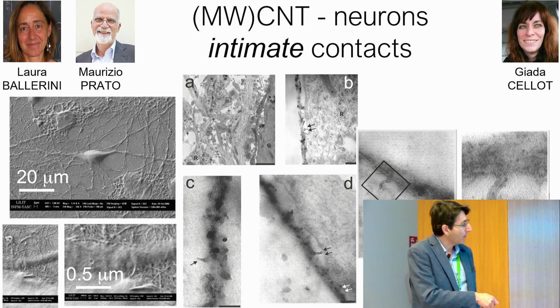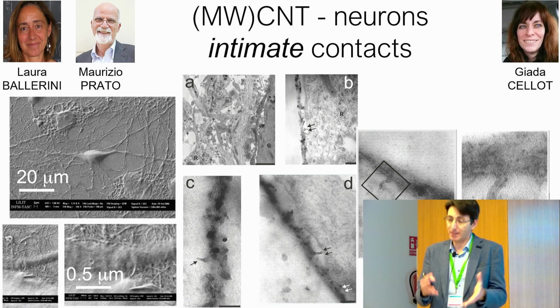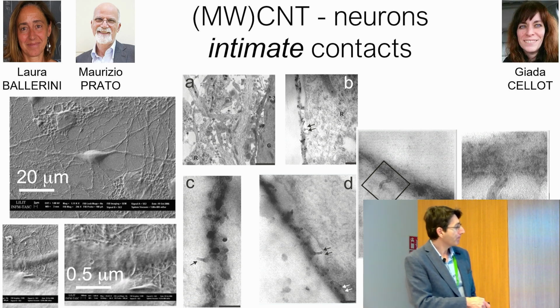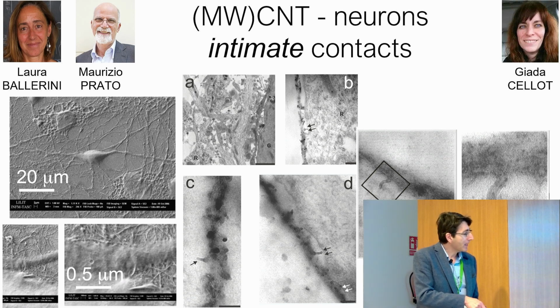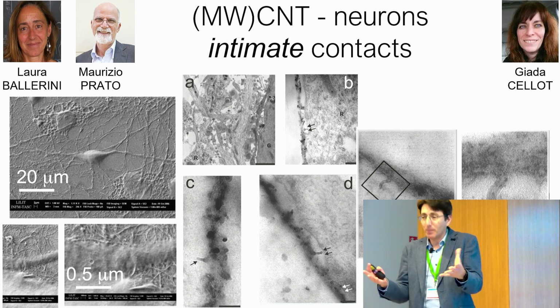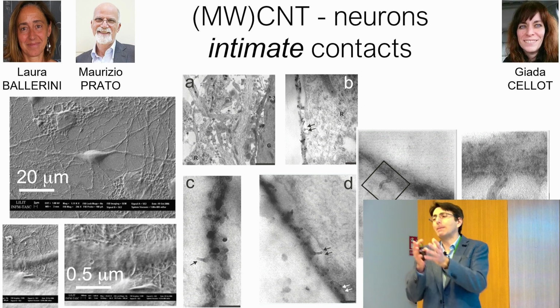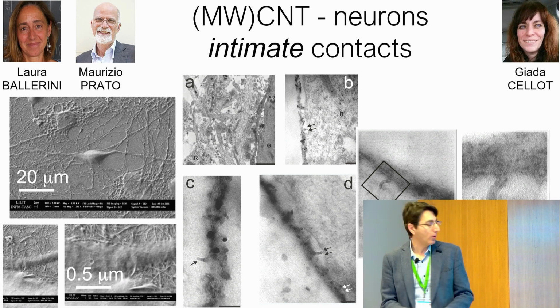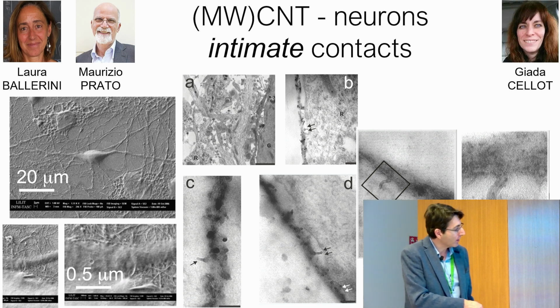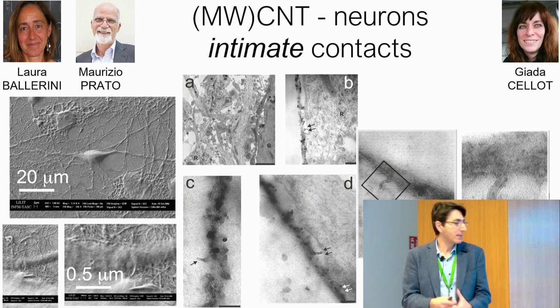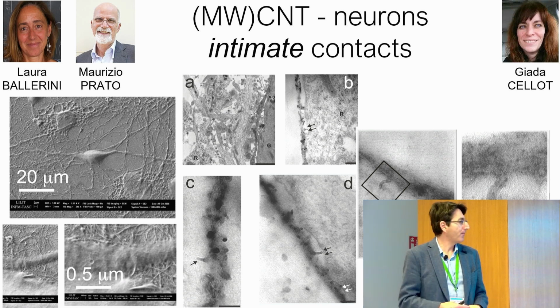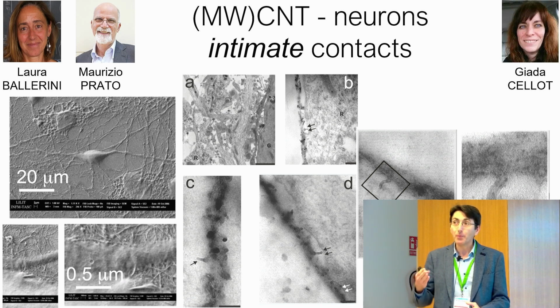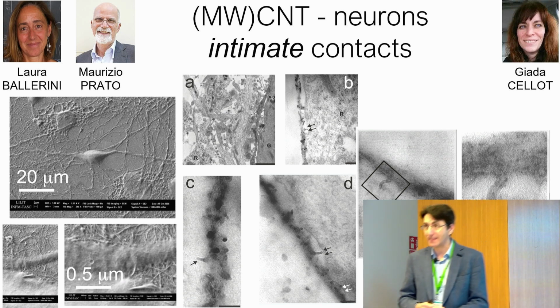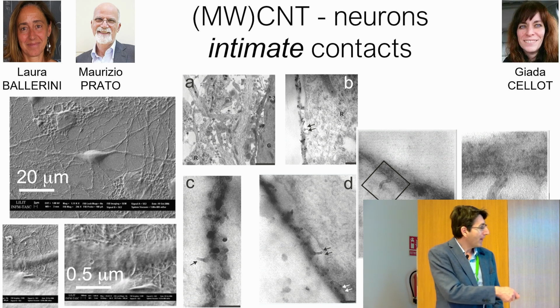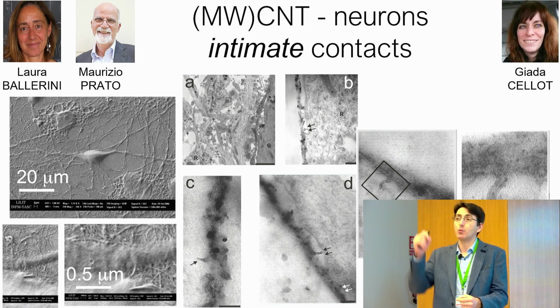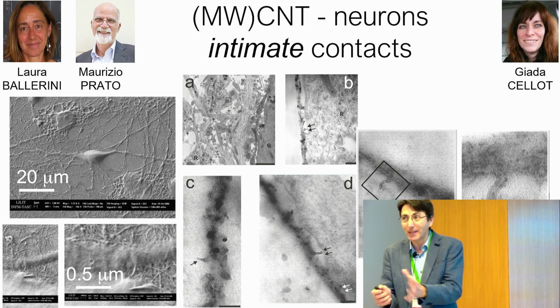these are scanning electron microscopy images of cultured neurons. So this is not in vivo, it's not implanted, it's just ex vivo developing neurons from rats. Something intriguing at the time was looking at the bundles of nanotubes that spontaneously, randomly, because we don't yet have a way to control the deposition or growth of carbon nanotubes in a very precise way, get in close proximity with neuronal membranes. And as I said, they are conductive, so it fed my imagination of some sort of nanoscopic electrodes that could pinch the membrane of a cell, realizing the best of both worlds: a fancy extracellular-matrix-mimicking feature, as well as intracellular access. I can tell you, spoiling the surprise, we didn't manage yet.